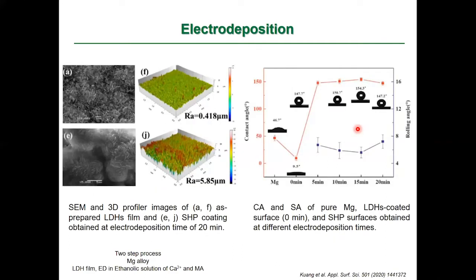So this is another example, done in a two-step process on magnesium. The first step was a layered double hydroxide formation. See, this is a magnesium bare surface having a contact angle of 46. On layered double hydroxide formation, it becomes super hydrophilic. But on subsequent electrodeposition, with 5 minutes and depending upon the time, the superhydrophobicity is achieved.